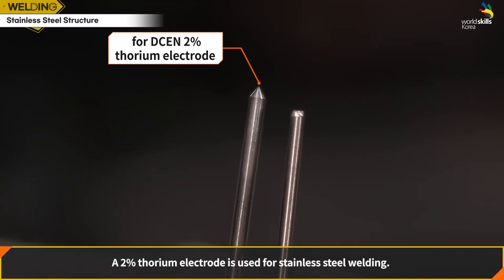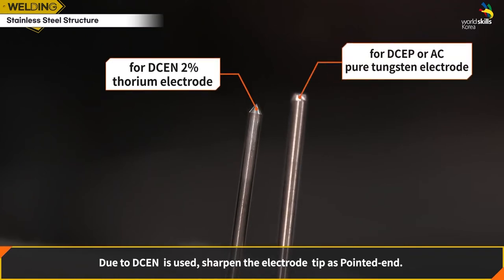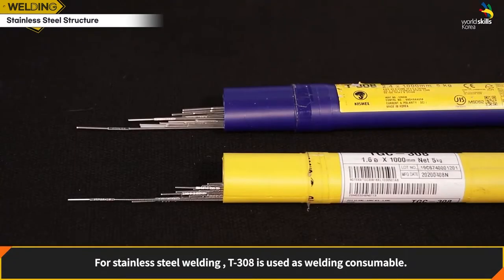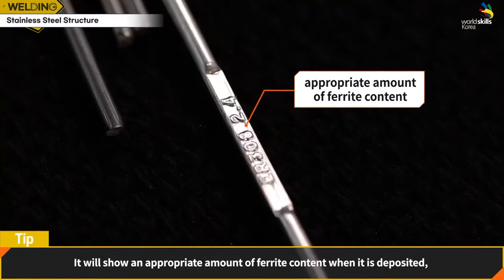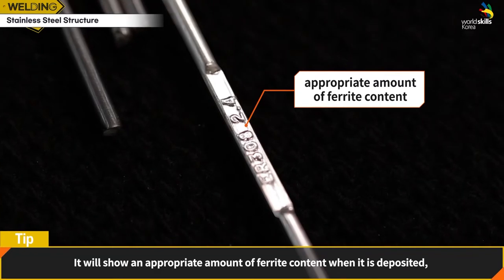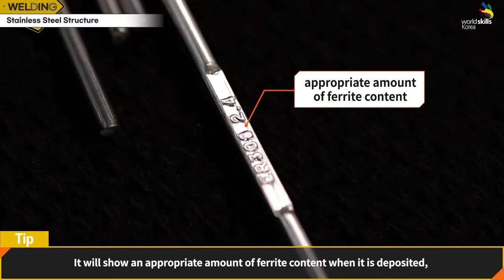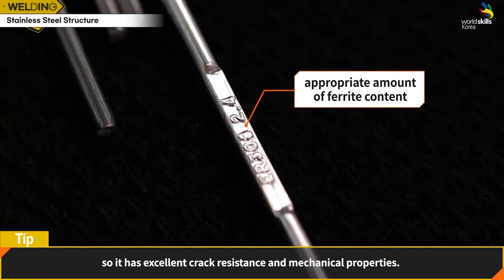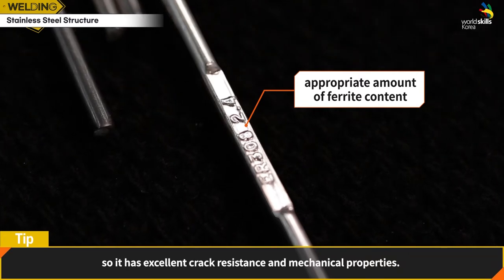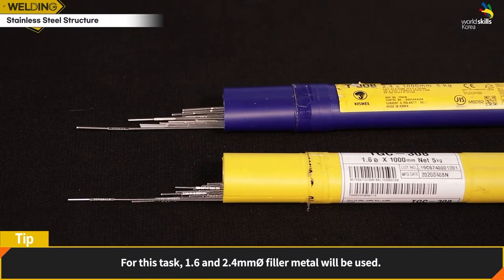A 2% thorium electrode is used for stainless steel welding. Because DCEN is used, sharpen the electrode tip as a pointed end. For stainless steel welding, T308 is used as the welding rod. It will show an appropriate amount of ferrite content when it is deposited, so it has excellent crack resistance and mechanical properties. For this task, 1.6 and 2.4 mm filler metal will be used.